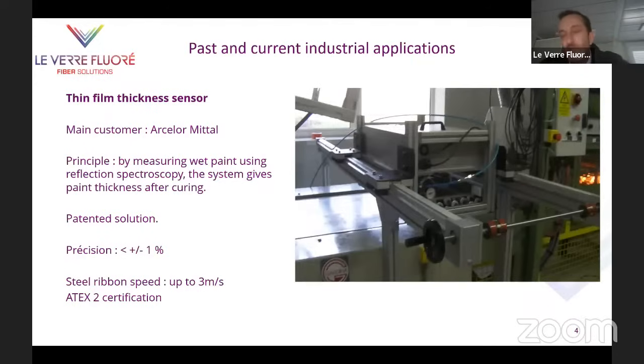The second application, which we developed 15 years ago with ArcelorMittal, is a wet paint thickness sensor for coil coating. The main customer was ArcelorMittal. It is just reflection spectroscopy. But the interest of the technology is that you measure when the paint is wet, and it gives you the thickness once the paint is dry after curing. Because actually the spectroscopy absorption relies mainly on pigment, not on solvent. So once the solvent is removed, the signal is the same.